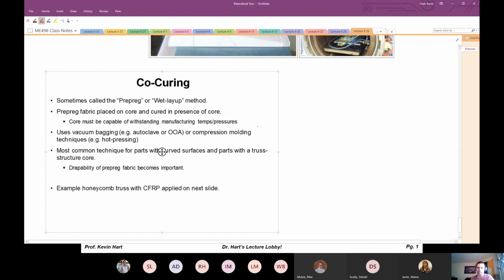So you have to make sure that if you're going to use this methodology, whatever manufacturing process is required for the face sheets, let's say you're curing at 150 C under 3 atmospheres of pressure, that your core can handle that. If your core is just going to get crushed, then that's a terrible manufacturing idea. We'll use vacuum bagging or out of autoclave techniques, or compression molding techniques like hot pressing. This is the most common technique for parts with curved surfaces and truss structured core.